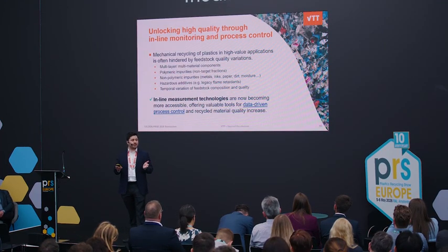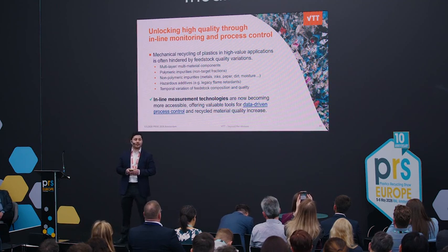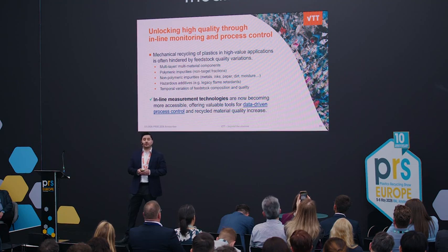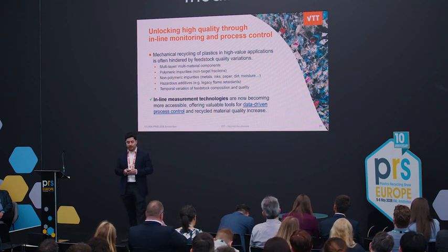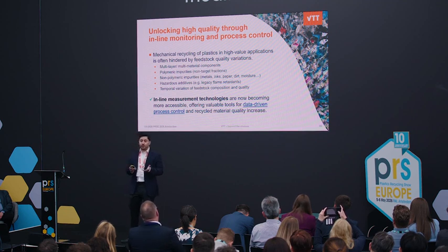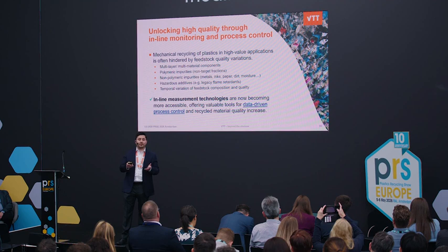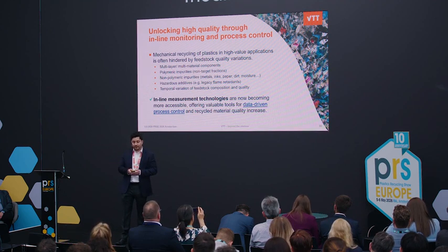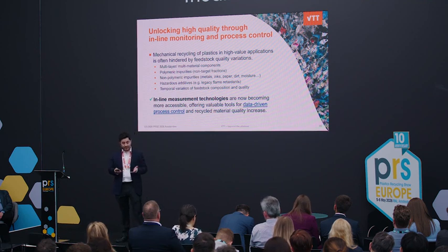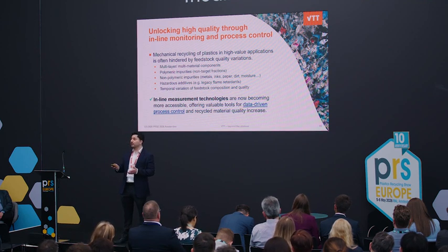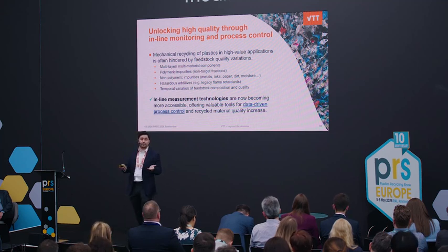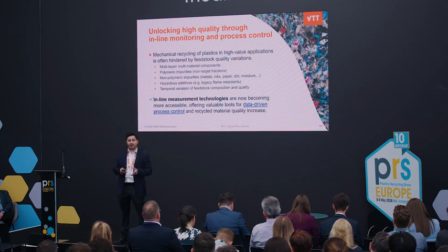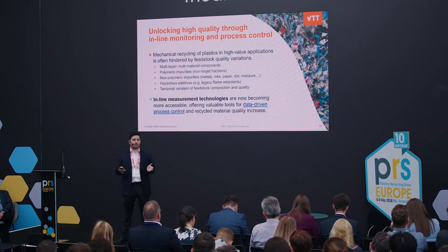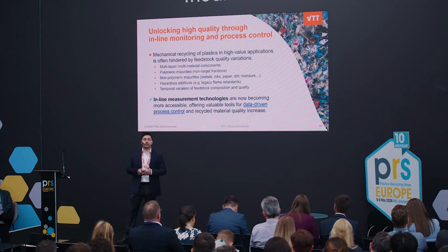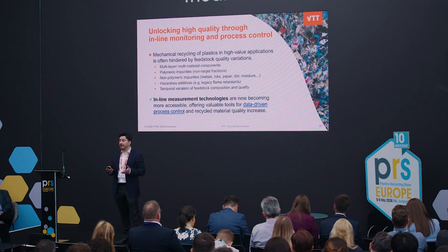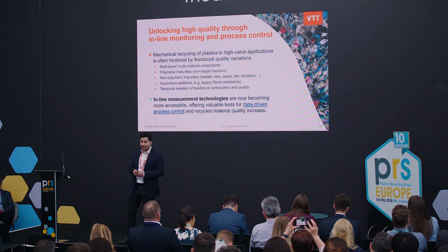When you have your recycled feedstock, I think many of us know that we might have very different levels of fluctuations in our feedstock. You might have multi-layer, multi-material components. You will have polymeric impurities as well as non-polymeric impurities. You might have polypropylene, but you might end up with some PET inside. And you might have hazardous additives, for instance, legacy flame retardants or PFAS. And of course, you have fluctuation of properties in the feedstock within the batch or between the batches. So with these inline measurement technologies, we are aiming to monitor all of these properties continuously and teach our line to decide itself how to behave and how to react during the extrusion and to adapt the extrusion parameters.